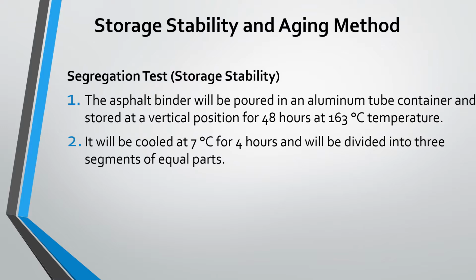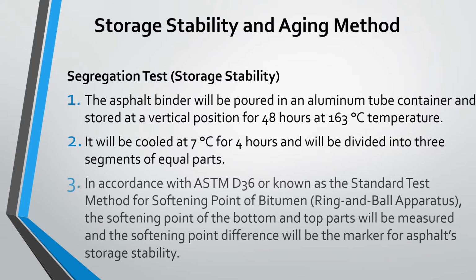In accordance with ASTM D36, known as the standard test method for softening point of bitumen using the ring and ball apparatus, the softening point of the bottom and top parts will be measured, and the softening point difference will be the marker for asphalt storage stability.